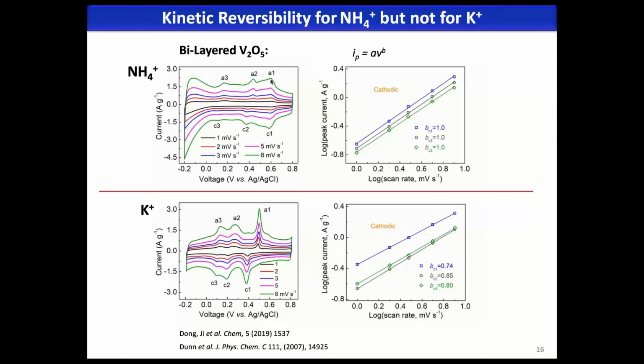It means the polarization is very small, and if you read the book, it actually talks about adsorption of redox species on the surface of the electrode. In the book they use mercury and some other microelectrode, and here we don't have those surfaces to talk about. We have the lattices, and these ions are actually inserted inside the lattices. So if you think about adsorption, we may have some flavors of covalency in the bonding for ammonium with the V2O5 lattices, potentially between the hydrogen of ammonium and the oxygen of V2O5 in terms of some hydrogen bonding. Potassium doesn't have that luxury. Potassium is a single sphere, a very homogeneous ion.